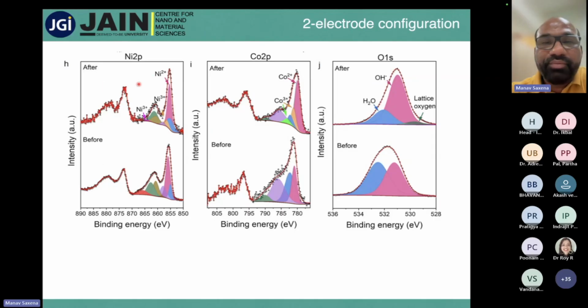After the device fabrication, we have opened it and we have done the XPS, and we see that there is a formation of cobalt 3+ as well as nickel 3+, and that is now not reversible. It is a stable kind of thing, and it becomes nickel 3+, and that is why the performance of the device is decreasing after 30,000 cycles. So nickel 2+ or cobalt 2+ converted to the plus 3 oxidation state, and it is not coming back.